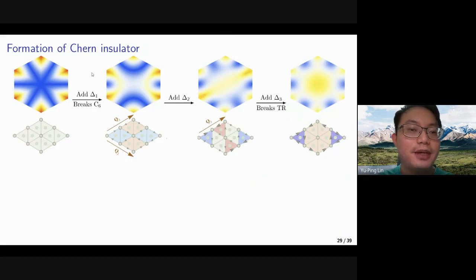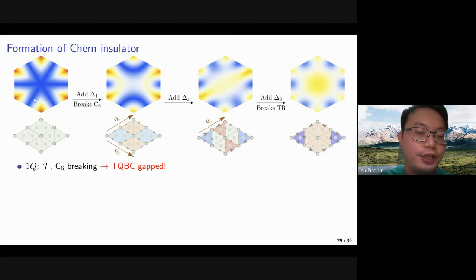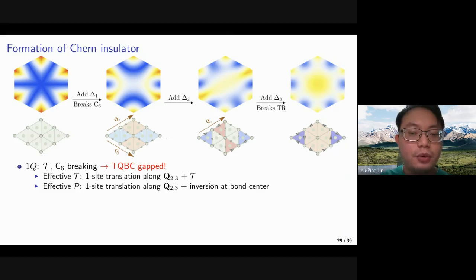So we could understand further about the formation of the Chern insulator. First, if we introduce the 1Q order, it will break the time reversal and the C6 symmetry. So we will gap out the quadratic band crossing. And the Fermi level will now become a null point and some nodal curves. Here we will have an effective time reversal symmetry, which is realized by combining a one-site translation, where the current along this direction goes to here, and by applying a time reversal so that the current direction is reversed. Meanwhile, we could have an effective inversion, where we again apply a translation and an inversion with respect to the bond, so that it also reverses the current order.